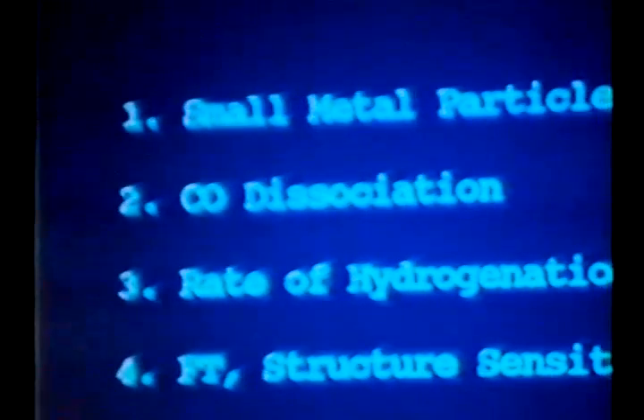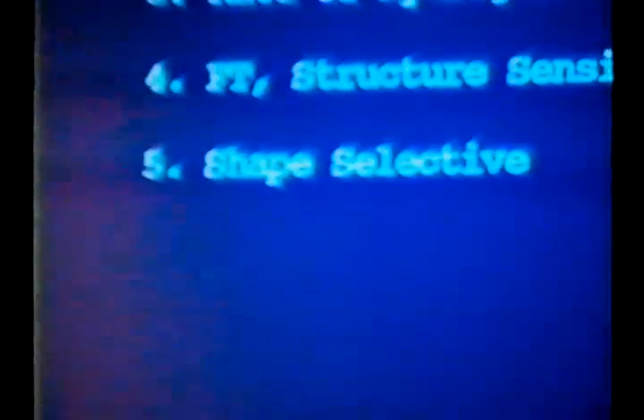Well, what do we see? We see that these small metal particles have a very high olefin selectivity. That's the good news. It seems that CO dissociation is decreased somewhat. The rate of hydrogenation must be depressed because we see a lot of olefins. It seems to be a structure-sensitive reaction. This is consistent with their data as well as the data we have. And there may be a shape-selective effect for these very small particles.